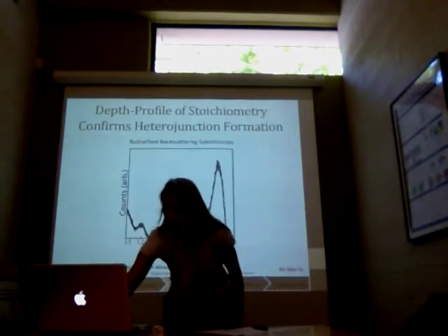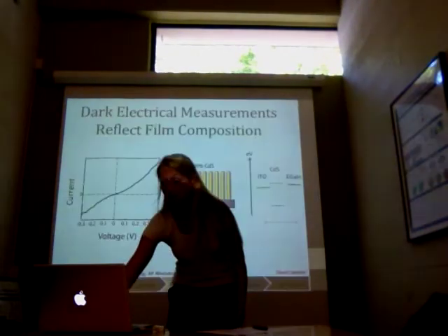There haven't been a lot of really good studies on copper sulfide in general, and the reason for that is because it doesn't like to be stoichiometric. We're able to get it to be stoichiometric using our ion exchange technique, but it loves to lose copper ions and become copper deficient. And as you start to become copper deficient, the phase diagram, you move to a different part of the phase diagram that has totally different behavior.